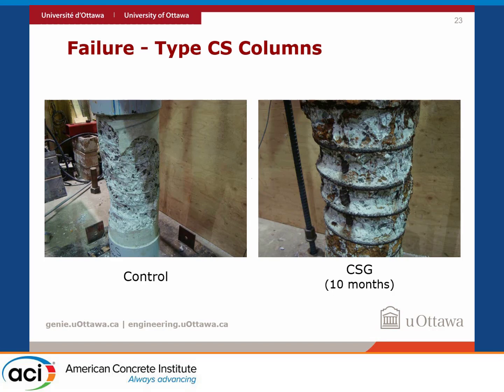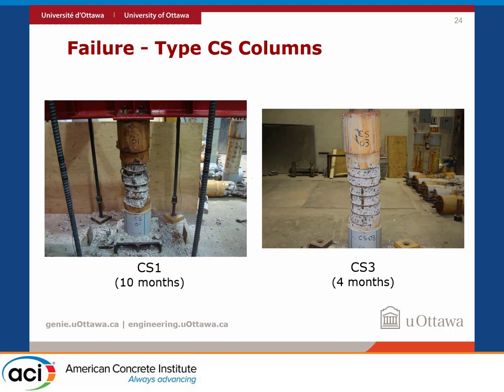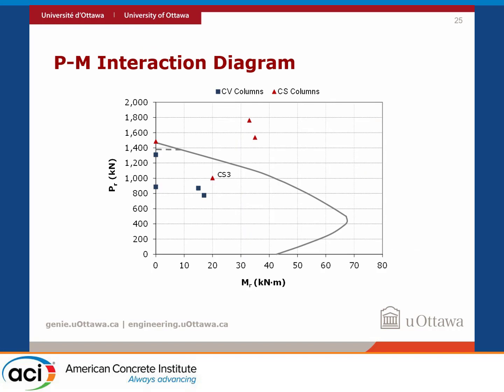Although you can see, I don't know if you can appreciate it, a little bit of buckling of the longitudinal reinforcement on these specimens after attaining the second peak. And these are the other two types of columns. So I have plotted here the results versus the design load-moment interaction diagram, and we can see that those columns that were corroded along the longitudinal reinforcement failed in a region where they were supposed to be safe. So this is a problem here. However, for the other columns, we observed that the confinement was kept after the second peak, and even though the spirals were corroded, it did not affect the column behavior much.